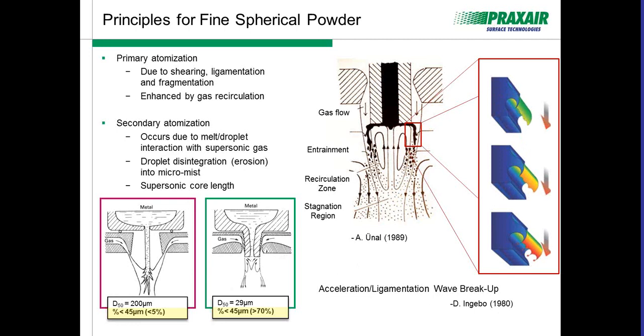That's going to be the droplets that are less than 45 microns in diameter. And how you can control that is really given by the gas to metal ratio, as well as your supersonic core length. There's got to be a balance there that has to be understood by your atomization engineer to create the most ideal distribution of droplets to maximize the yield of these powders.